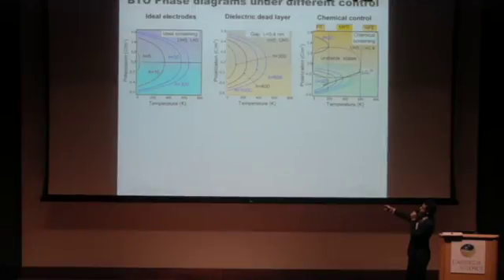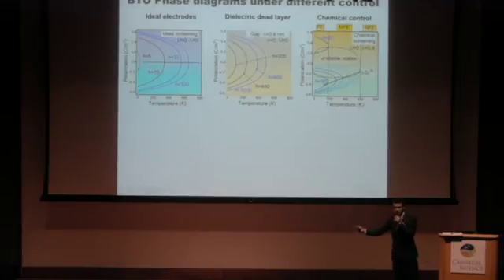As you go to lower temperatures, you start to have two polarization states which are equal in energy, so it's entirely symmetric. There's nothing very interesting happening here. This is what everybody has seen from 40, 50 years ago at least. You can also introduce a dielectric dead layer. This is basically just a finite thickness over which the potential will drop to the external applied potential. It doesn't change the calculations at all. Basically, you have a slightly reduced polarization, but there's nothing qualitatively different about these two cases.